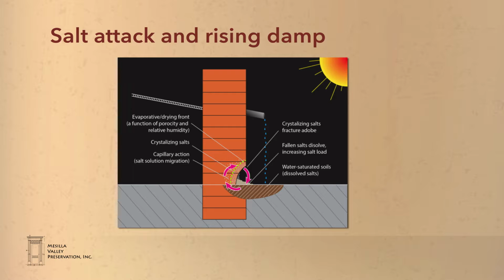So you can see that this is a vicious cycle. It literally only gets worse with time as salts continue to concentrate. The salt concentration only rises. If there is one thing to take away from this slide, it is that evaporation is just as important, if not more important, to this cycle than the moisture itself. Moisture is certainly an issue, but it is aridity and evaporation that is the driving force for the damage we see.